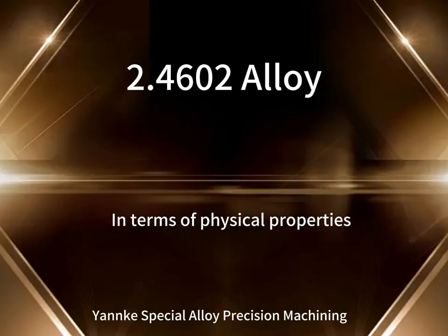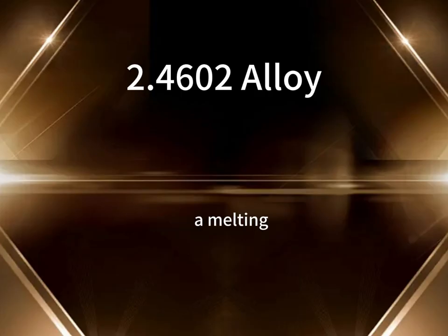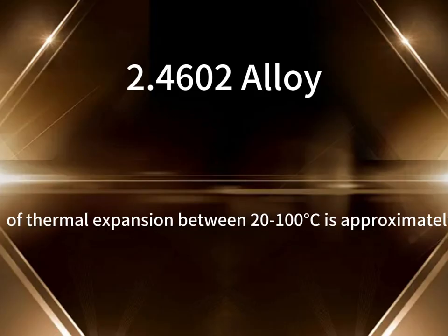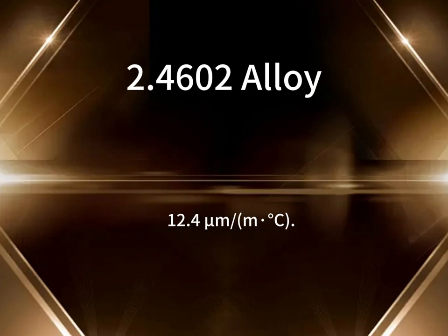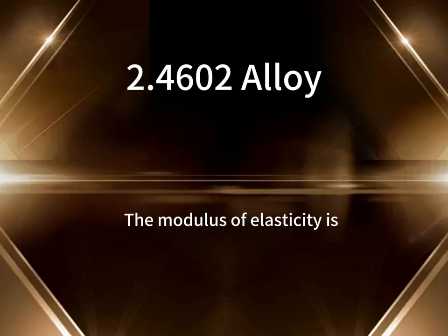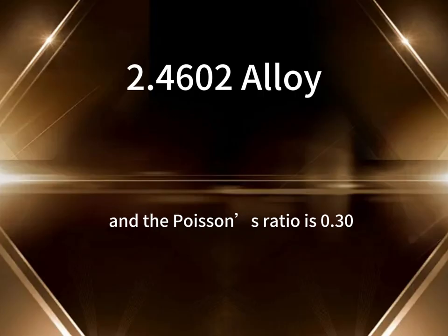In terms of physical properties, the alloy has a density of 8.69 g/cm³, a melting range of 1325 to 1370 degrees Celsius, and a thermal conductivity of 10.1 W/mK at 20 degrees Celsius. Its electrical resistivity is 1.14 μΩ·m, and the coefficient of thermal expansion between 20 and 100 degrees Celsius is approximately 12.4 μm/m·°C. The modulus of elasticity is 205 GPa, and the Poisson's ratio is 0.30.